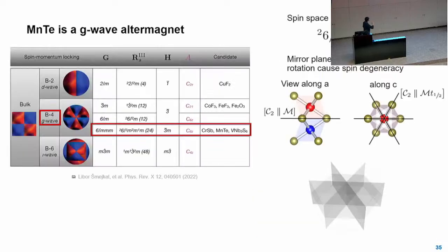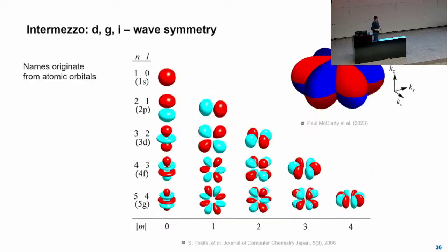So Libor, of course, figured out in more detail how to classify these altermagnets. I don't want to go into details here. I just want to say there are different types. He calls them D, G, and I wave. And this is in analogy to the atomic orbitals. You might remember, we have S, P, D, F, G orbitals. And in this analogy, if you take only the even ones, you see even angular momentum. And of course, we want some which have a finite angular momentum. So the S one is not interesting for us, let's say. But it starts with D. Then it's G, and then if you continue this, you would come to the I. So in our case, this manganese telluride is a G-wave altermagnet. Its band structure looks a bit like this, which is similar to one of the G-wave orbitals in atoms.